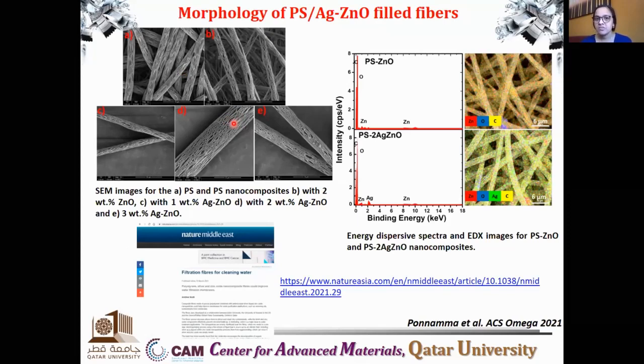One is a non-solvent. So while electrospinning, this non-solvent will induce phase separation inside the polymer. And due to this phase separation process, pores will be generated on the fiber itself. So you can see nice pores on the fiber.